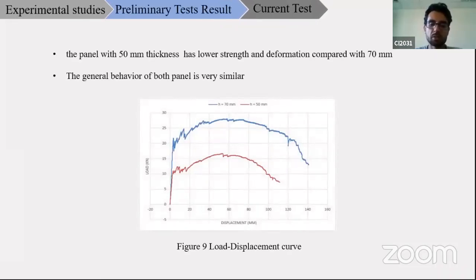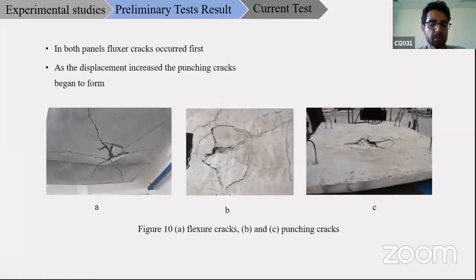As we see in the load deflection curve, the panel with 50 millimeter thickness has lower strength and deformation capacity compared with the 70 millimeter. However, the general behavior of both panels is very similar. In both panels, flexure cracks were observed first, extending from the midpoint toward the edges and forming yield lines. As the displacement increased, punching cracks began to form. And after the crack load, with increasing displacement, the punching cone began to separate, and the load started to decrease in both panels.